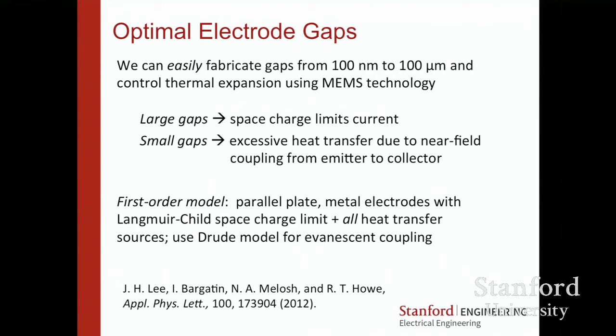So one question is, we can easily fabricate gaps from 100 nanometers and maybe even thinner to 100 microns. It gets harder in microfab with wafer bonding. That's kind of the easy sweet spot. Do we want to make large gaps? No. If it's 100 microns, you're going to get space charge. You're going to get charge buildup across this gap. It's well known from vacuum tube days.